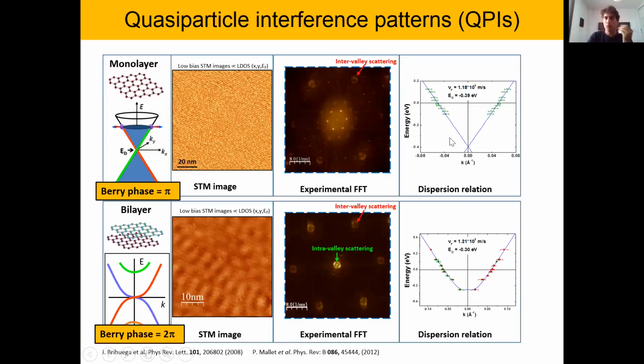Okay, that's a good question. So in our case here, when we try to measure at lower energies, we lose the signal coming from graphene because we start to get a lot of signal from the substrate. Those measurements are essentially the only ones that I will be showing on graphene grown on the silicon face. So here we have the substrate, which is just close by, and we have those electrons which were going to the graphene layer. This is why we have it doped. And then when we try to go to these voltages, we start to see signal from the substrate. So we cannot probe essentially graphene. We lose the signal from it. So I hope this answered the question.